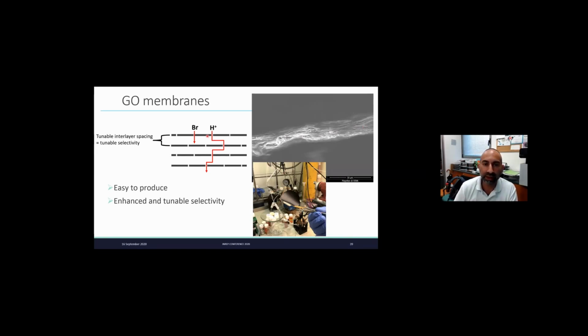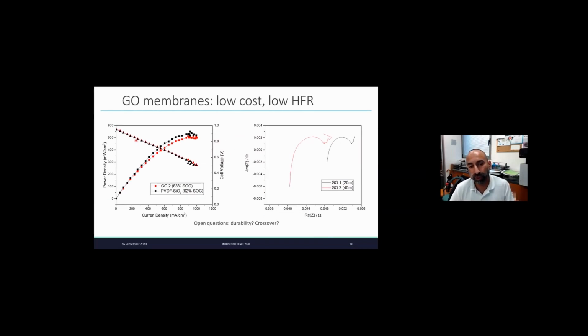And the idea is that you've got a lot of layers of graphene oxide and the proton will go inside the pores, but the bromine will be blocked because you can also control the interlayer species that you have between the layers. And it works. So what we did is to compare our standard membrane, which is a PVDF-SiO2 developed by the group of Professor Pellet, with graphene oxide on top of a separator, and we got the same performance for the two.